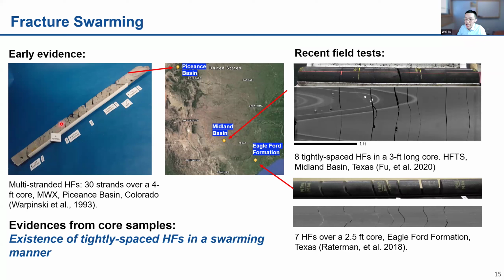It really challenged people's understanding at that time. But at that time, it was mostly attributed to the overpressure of the formation or the existence of microcracks. Later on, from some recent field tests, we started to observe similar behaviors. This one is in the Midland Basin, where we've seen 8 tightly spaced hydraulic fractures in a 3-foot-long core. This is from the Hydraulic Fracturing Test Site, HFTS1. The bottom one shows another core sample with 7 hydraulic fractures, done by ConocoPhillips at the Eagle Ford Formation.